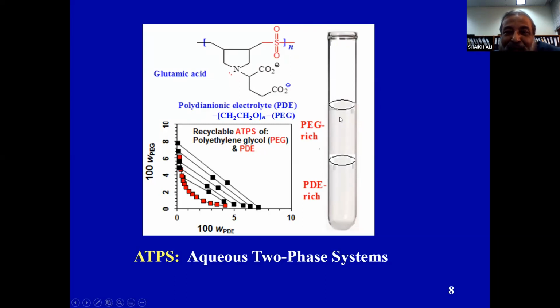glycol, and when you add them into the water, both of them are water soluble. But in water, it is not an exception. It is the reality that they develop into two phases. One is rich in this polymer, another is rich in polyethylene glycol. We have developed many aqueous two-phase systems where we can inject biomolecules like proteins, and if you have